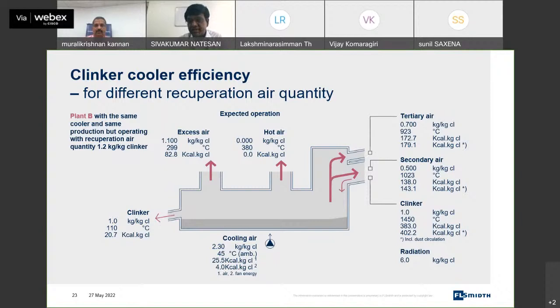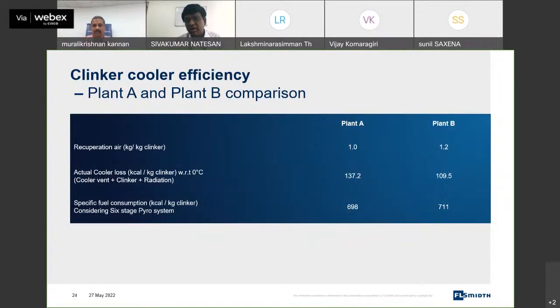The cooler is not performing better. It is the same cooler, but by taking more air back to the system, the efficiency parameter looks to be better. But ultimately, if you see the realistic picture, when we take more air back into the system, that air has to be heated in the burning zone, and it costs us fuel. So by just comparing the actual cooler loss, the cooler looks to be better. But when you see the real parameter which we are worried about, the heat consumption is high. So it's always better to have the heat consumption as the performance parameter to evaluate a cooler than the cooler losses or cooler efficiency, which is a good parameter to get the feel of how the cooler is performing. But it is affected by the other process parameters in the system also.